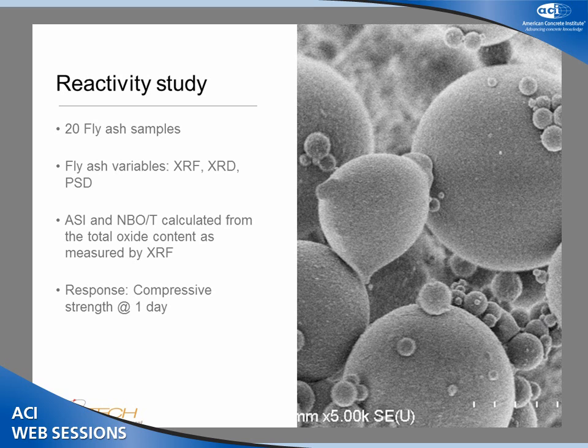So what we did, we took 20 fly ash samples that we were using commonly, from low strength to higher strength. We ran chemical composition, and crystallographic characteristics by XRD, qualitative and quantitative. We also obtained the particle size distribution of the fly ashes. And we used a couple of glass manufacturing parameters, which are the alumina saturation index and the non-bridging oxygens per tetrahedron. They are calculated directly from the oxide content as measured by XRF. And the response that we used was compressive strength at 1 day.